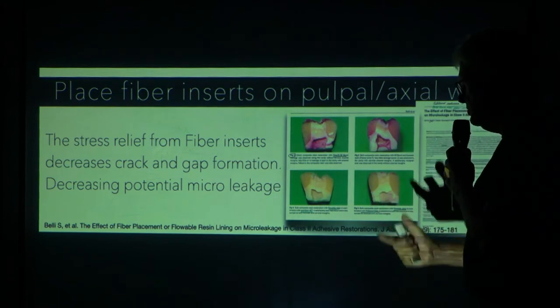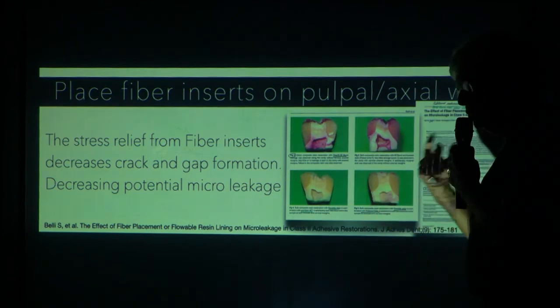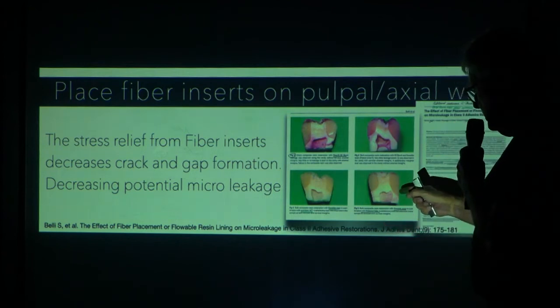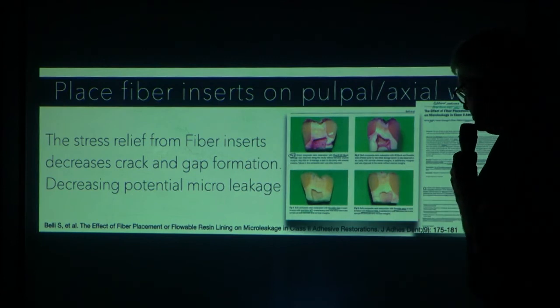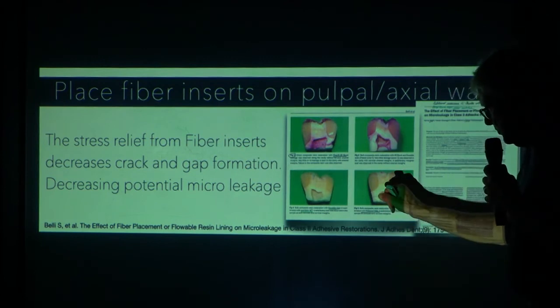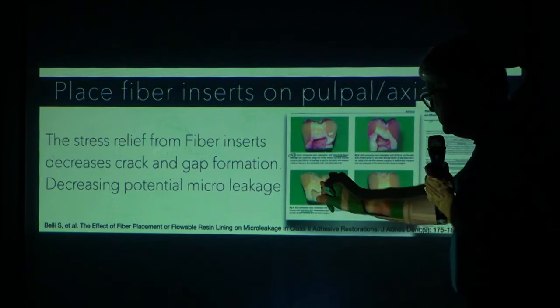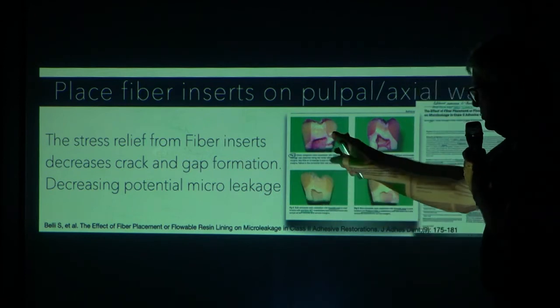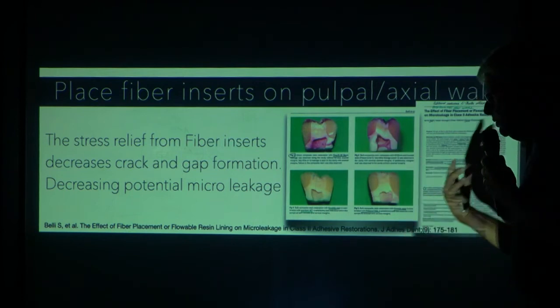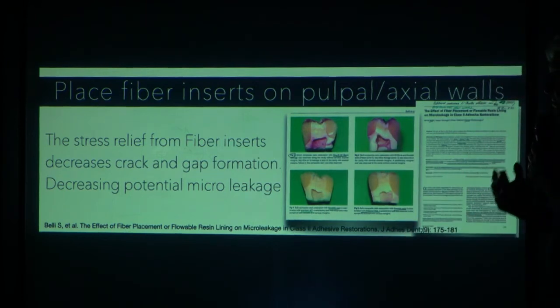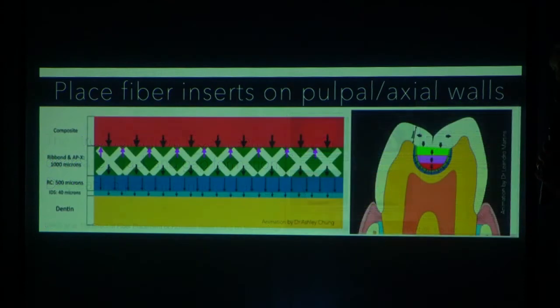That's stress. But still, if you stress scientifically in a situation and then you remove stress, then your ability to keep your bond and stop the leakage is even better. But this fiber that's right here and right here and right here is stopping the leakage here, here, here. When you read this paper, you see that the stress relief from the fiber insert decreases the gap formation, and that decreases the potential of microleakage. And microleakage is the beginning of all the biologic failures.